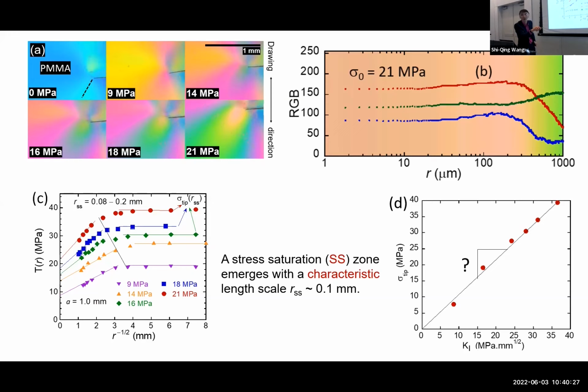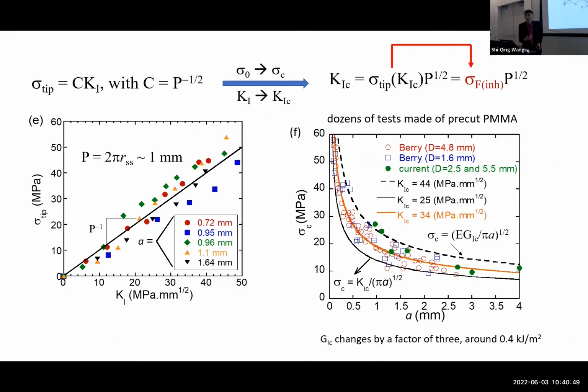If it's linear, that slope, just by dimensional analysis, involves a length scale. The tip stress builds up linearly. This is just normalized loading parameter involving the cut size. If you have different cut sizes, you can collapse all the data there. In more detail, you can do a different cut length, same loading parameter. What happens is this linearity holds all the way to the point of breaking. As I said, this linearity means that a length scale pops out. And that length scale is about a fraction of a millimeter, a tenth of a millimeter.